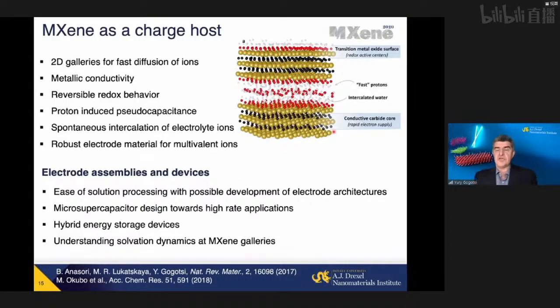So why are they attractive? First, as I mentioned, they are highly conducting. They're actually probably the most conducting of materials used in energy storage today, at least titanium carbide MXene. Their surface looks like transition metal oxide, hydroxide, fluoride. It's actually an oxygen-terminated surface, predicted by DFT to be the best one for a variety of energy storage applications. And these layers of transition metal with electrons available for conductance allow fast transport of electrons, and galleries between the layers allow for transport of ions.